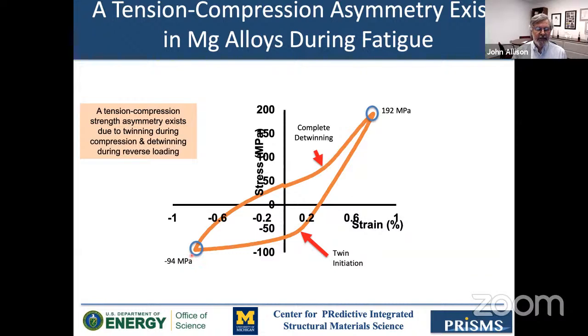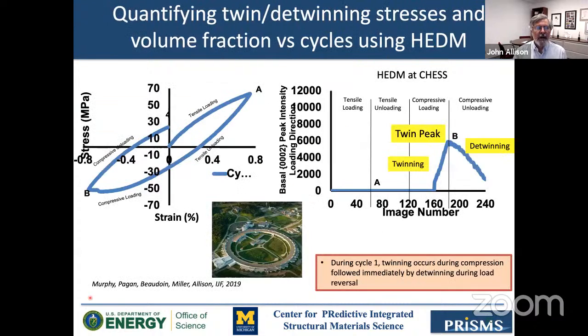You also see the peaks, and these are constant strain; they are to balance strain. So this is the strain in tension as in compression. And so this strain in compression goes to 94 MPa, whereas that same strain in tension gives 192 MPa. So this can have significant effects on how damage is accumulated and how you account for cyclic deformation. And so that's why this is of interest.